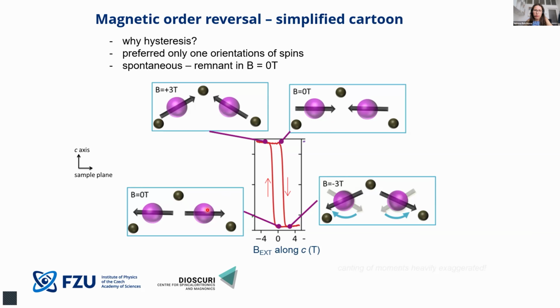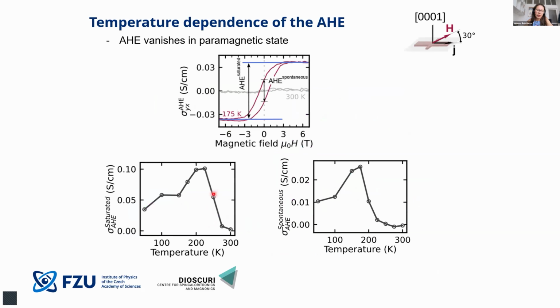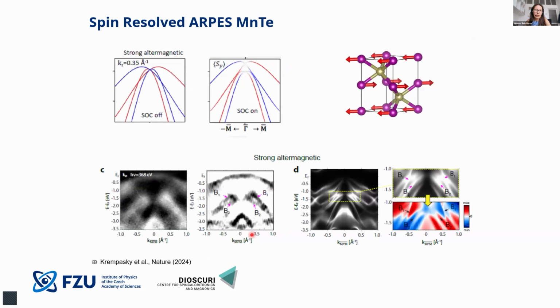And now when this is measured systematically at various temperatures, one can define something which I call here the spontaneous effect, which is the effect present in really zero magnetic field, and the effect which is called saturated. One can also see here that both of these are basically vanishing when we approach the critical temperature of the manganese telluride, around 310 Kelvin. I will not go into more detail on this system for time reasons, but I want to highlight that this is one of the materials which also has the spin splitting confirmed by ARPES, by Juraj Krempansky and others. There are many beautiful works around already.